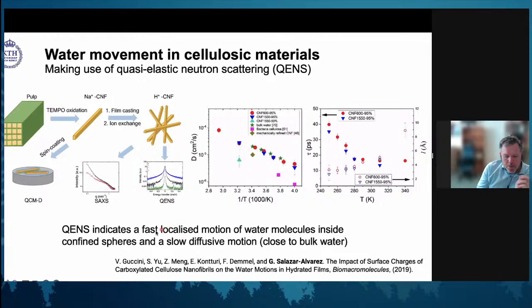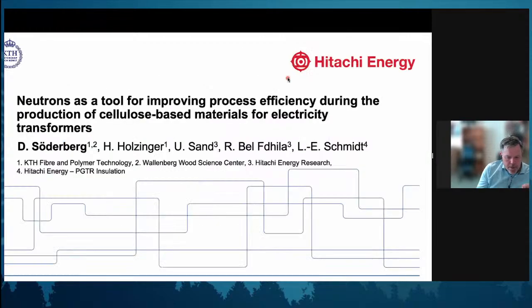That makes it possible to separate the diffusion that happens in the spheres that we saw when we were doing our grazing incidence measurements from the slower diffusive motion that can also be seen as part of the structure itself. So I suggest this is an interesting technique. It has challenges. We are going to try to do it ourselves, but these are the first that I've seen doing it. And as I said, it doesn't work with films. It needs much thicker objects. So that's two ways of using neutrons.